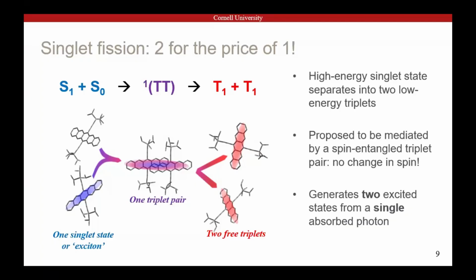And this has been studied on and off for about 60 years now. The most recent wave of singlet fission research was sparked by the idea that you could use it to make better solar cells. And in kind of the typical parlance of spectroscopy, we could say, well, we're starting in this bright singlet manifold. We're going into the dark triplet manifold. And it's harder to pin down what exactly this triplet pair state should be, but because it's made of 2 excited states, so it's got multiple excited electrons, and it's made of triplets, which are typically a bad thing, there are lots of reasons why this state itself should be dark.